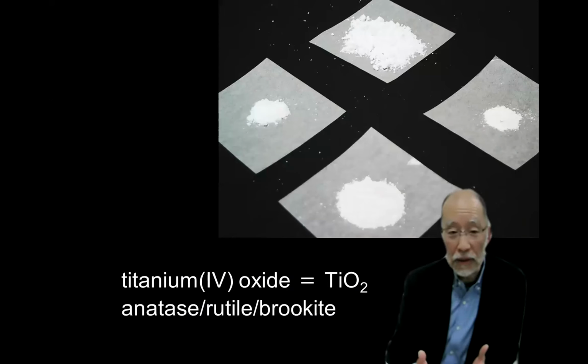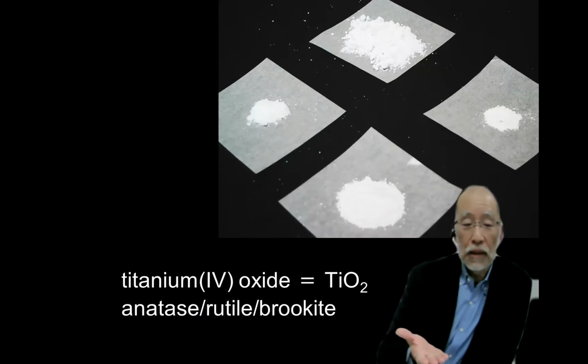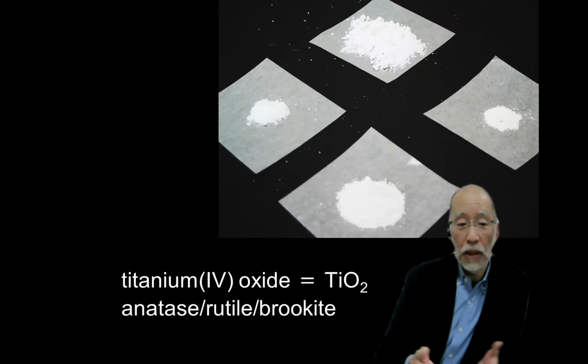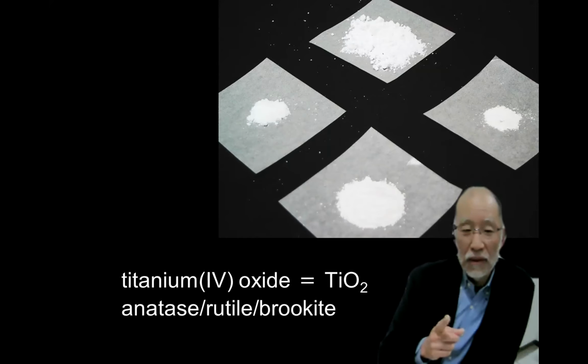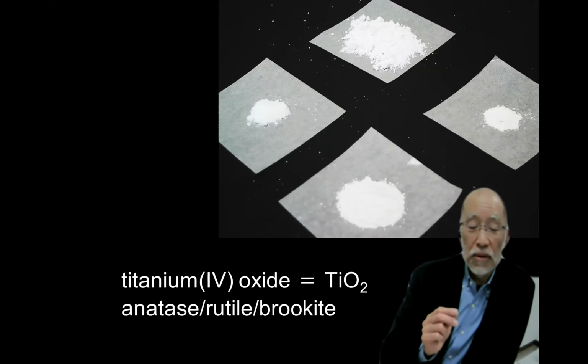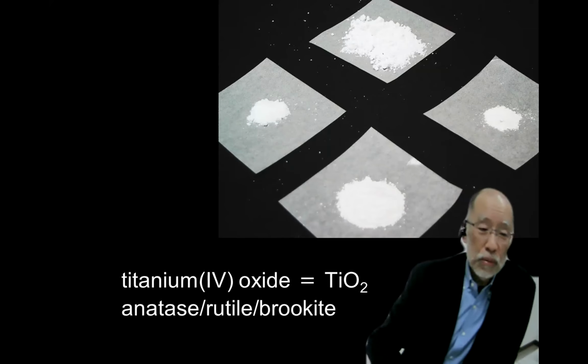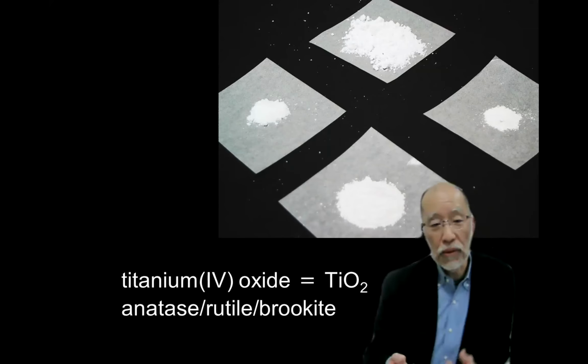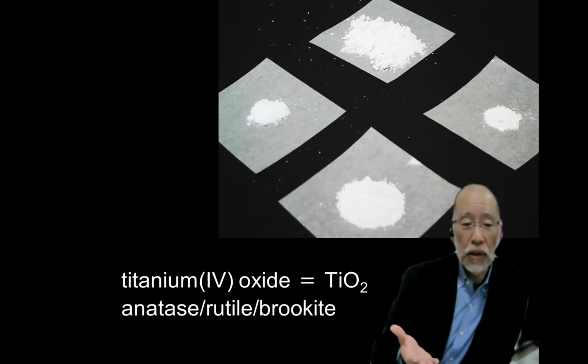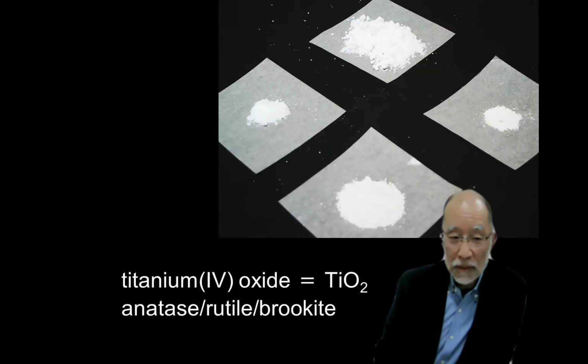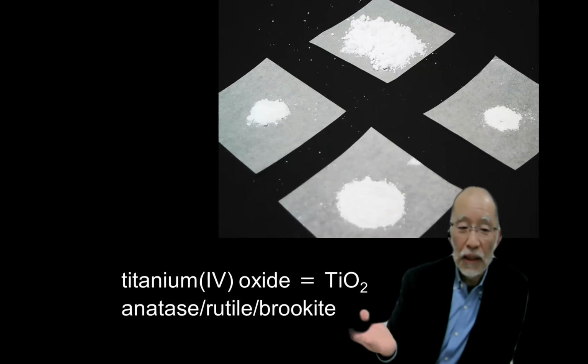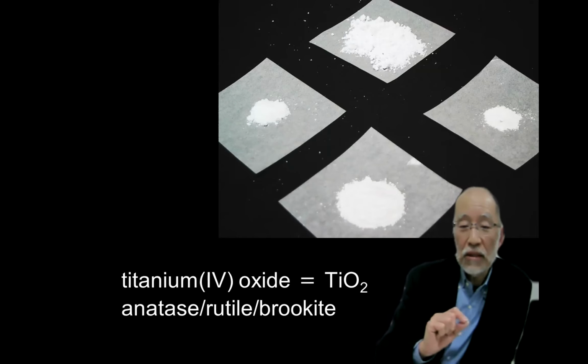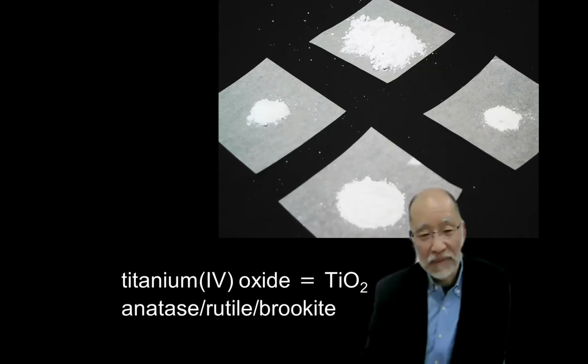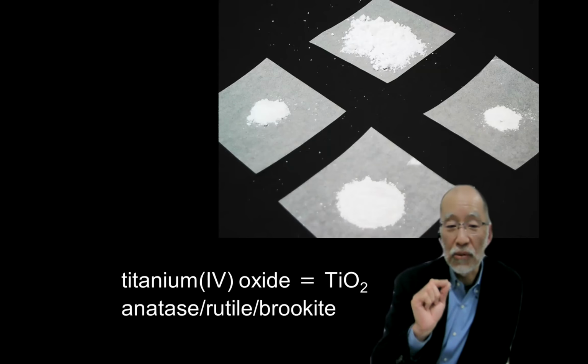And in the field of inorganic or material sciences, for example, titania is often used as a catalyst, a photocatalyst, or the other kind of materials. Yes. And what is the name? Titanium 4 oxide. And this just tells the composition, the ratio of number of atoms, Ti and O2 to be 1:2. And sometimes we measure the XRD, X-ray diffraction, to determine the crystalline structure into, for example, the anatase, rutile, brookite. This is the name of crystalline of titanium oxide. But we know, even if the same anatase or rutile or brookite structure, still those material is at least a bit different. So there is some difference, even if that crystalline structure is determined.